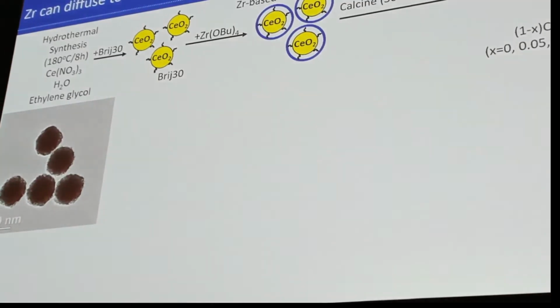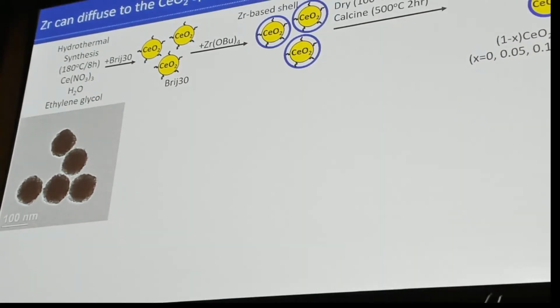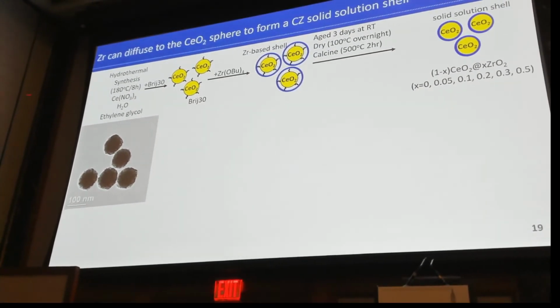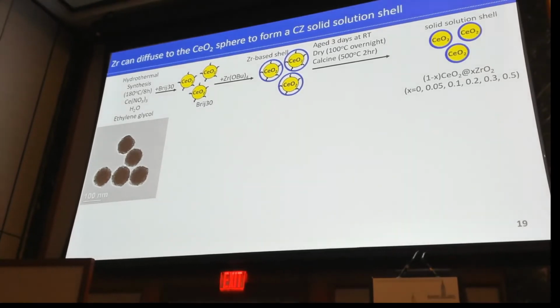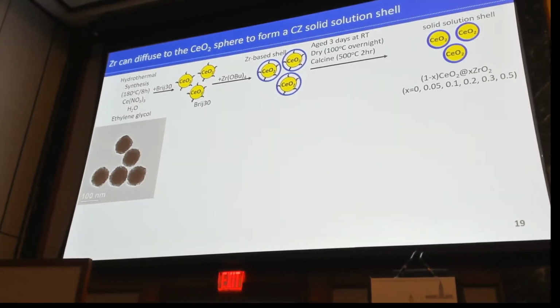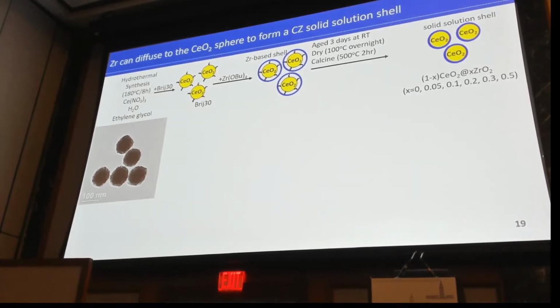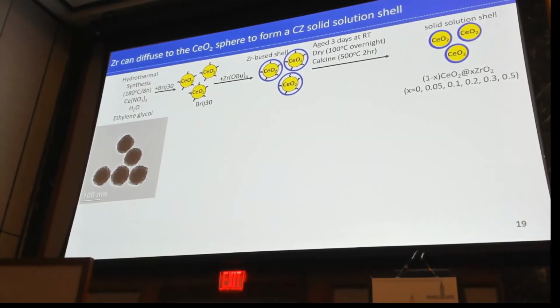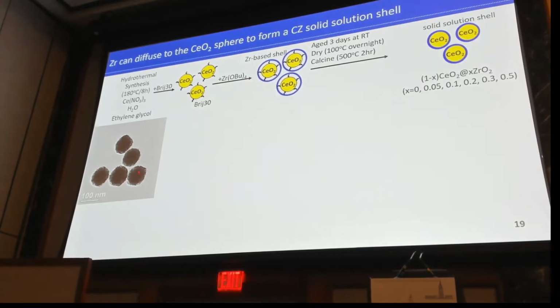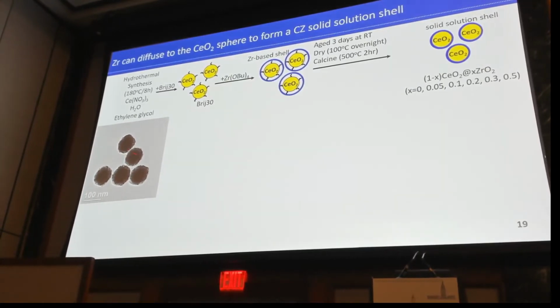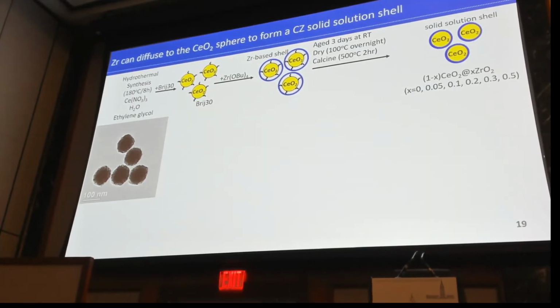So let me show you now how the ceria spheres were synthesized. They follow a hydrothermal synthesis where cerium nitrate, water, and ethylene glycol are mixed in an autoclave, and they are allowed to react at 180 degrees C for 8 hours. If we stop the reaction and collect the support, we can see that we are able to form these nice looking ceria spheres that have a diameter of around 100 nanometers.